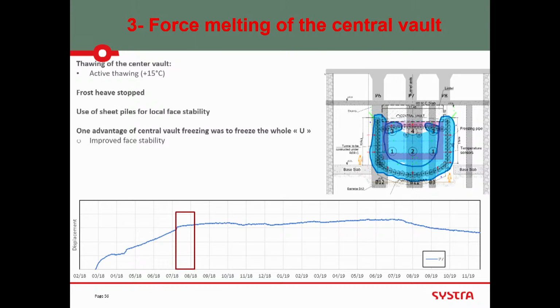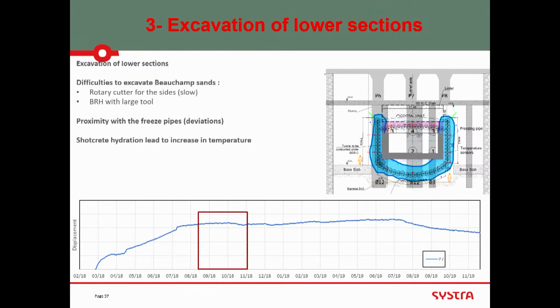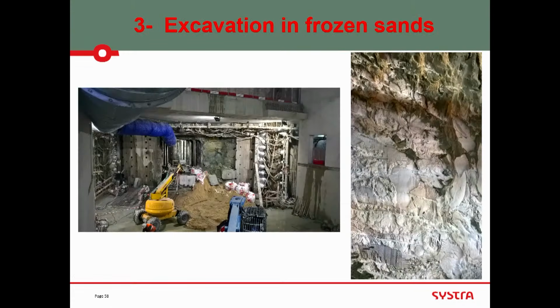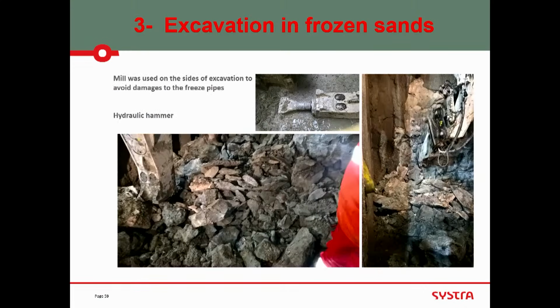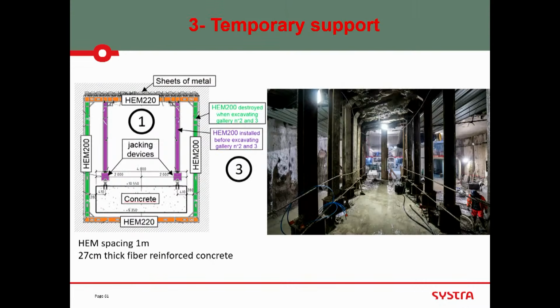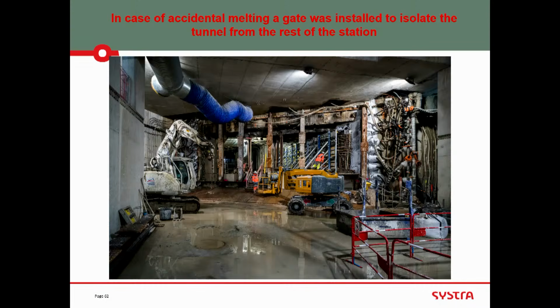Excavation of the top of the box. Excavation inside the box. So you see that this is quite stable. There is no uplift. This is how it works, seen from outside. And this is the face. Very hard to excavate with a grinding machine, hydraulic hammer. As we were very close to the pipe, the hydraulic hammer was not used, but the mill machine, or grinding machine, was used. This is the column for temporary works, the excavation of the box.